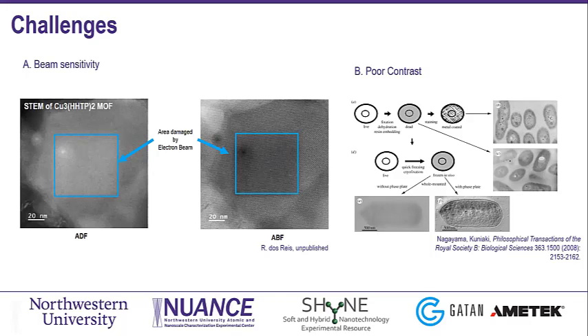So this is a nice example that shows one of the strategies to go around that using phase plates in TEM. This is a TEM image, right? So you see that without phase plate, you basically don't see too much from your biological sample here. So when you add that shift in phase using the phase plate here, you can enhance that contrast. This is something that can also be done in STEM and collected in a 4D STEM fashion. Again, just contact me. I can send you some references on that using phase STEM for that application.